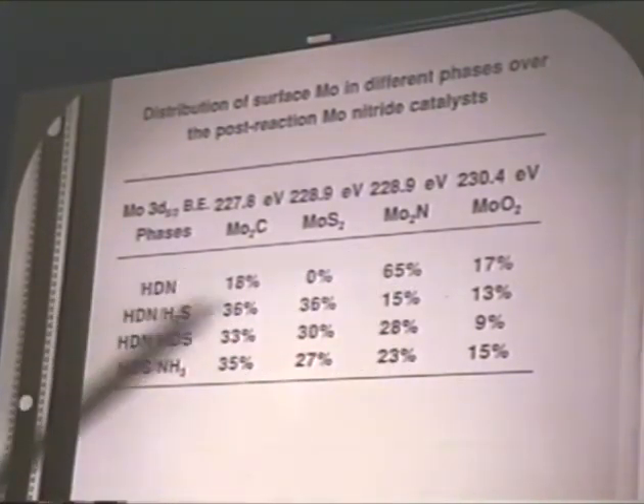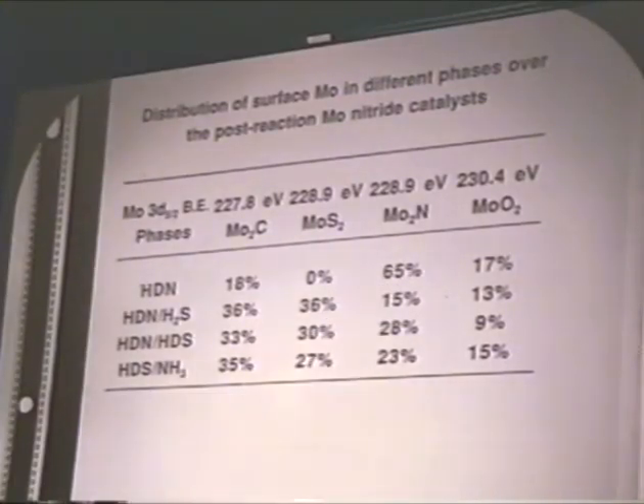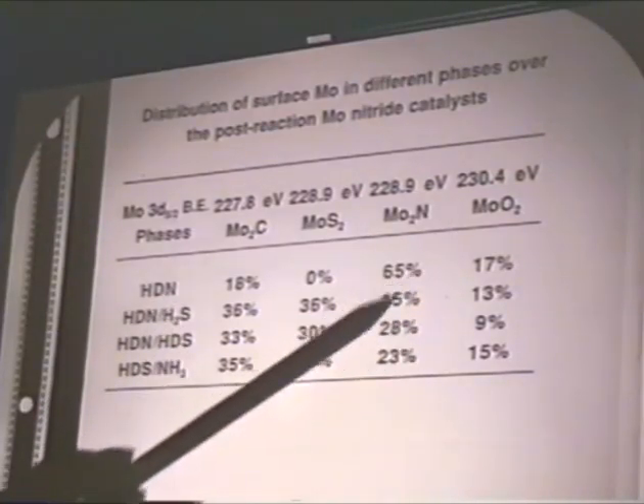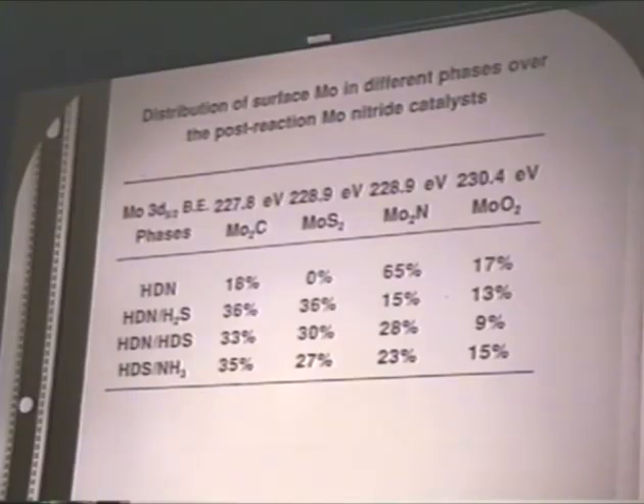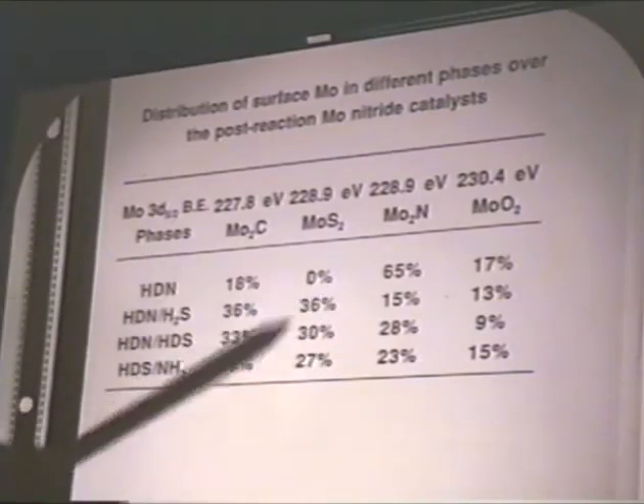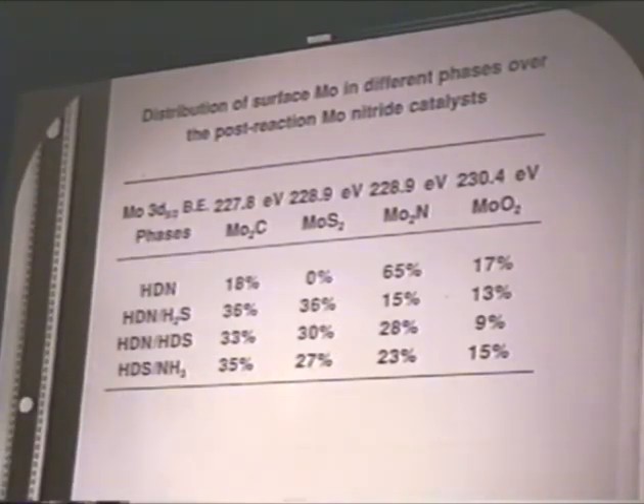Even when we don't have any sulfur compounds, there's some reduction of the nitride signal as we have seen earlier, but especially when we have the sulfur compounds, the amount of molybdenum nitride on the surface, the percentage, is really decreasing. And interestingly, we are obtaining some carbide phase, but maybe more importantly, we're also obtaining a sulfide phase. So we are suspecting that the reason we are obtaining a behavior over the nitride very similar to the sulfide catalyst when we have sulfur compounds present in the feed system is because part of the surface is being converted to a sulfide phase.